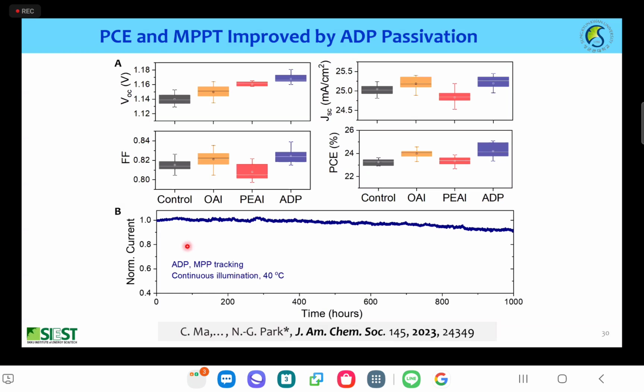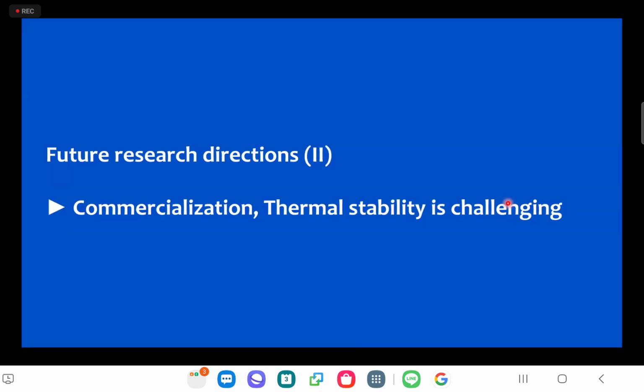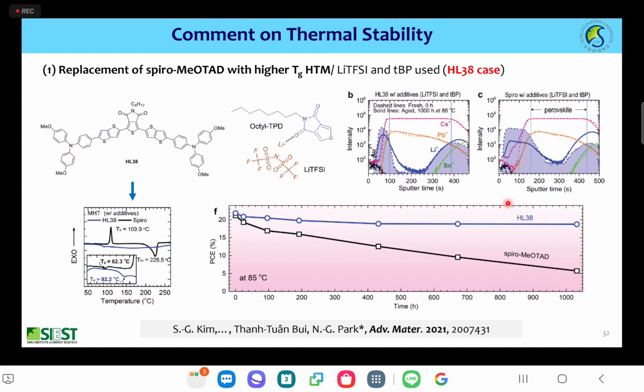And then again we show the pretty much stable perovskite solar cell based upon the ADP passivated perovskite film. And then let me move on to some commercialization issues. We have to focus on the stability, especially thermal stability is very important. Also, light stability nowadays becomes an important issue. And we currently use the spiro compound as the HTM material for the NIP structure. Then because of the low glass transition temperature, the thermal stability is not good.